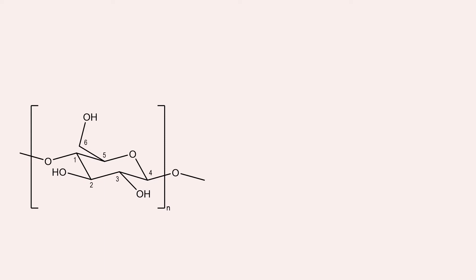In order to form nitrocellulose, cellulose is reacted with a mixture of concentrated nitric and concentrated sulfuric acids, forming nitrate esters in place of some of the hydroxyl groups. As you can see, there are multiple possible locations for the reaction to take place, so it cannot be exactly controlled, but reaction is about five times more likely at the group circled here, on account of it being the least sterically hindered, making it easier for the nitronium ion to attack.